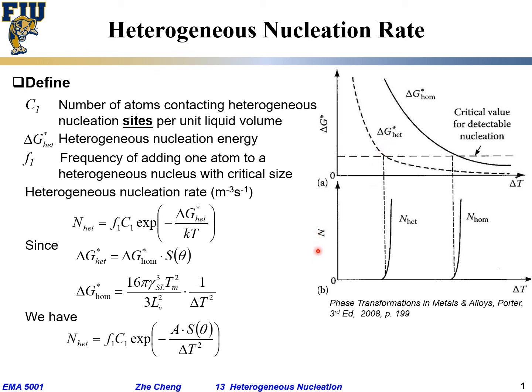And then the bottom plot is for N. What does N mean? Nucleation rate. For the same undercooling, heterogeneous, homogeneous, they would suddenly start, but the heterogeneous one would start at a much lower undercooling, which means at the same ΔT, the heterogeneous is way faster than homogeneous nucleation.